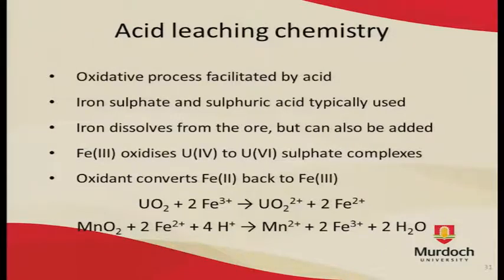Iron-3 oxidizes the uranium-4 within the mineral to water-soluble uranium-6. And the resulting iron-2 is converted back to iron-3 through the addition of oxidants. Pyrolusite, manganese dioxide, is a fairly common one, but hydrogen peroxide, sodium chlorate, and oxygen gas bubbled into solution have also been used elsewhere. The example reaction I've shown at the bottom just shows the leaching of uraninite with manganese dioxide as an oxidant.